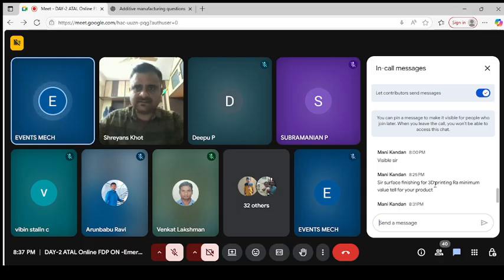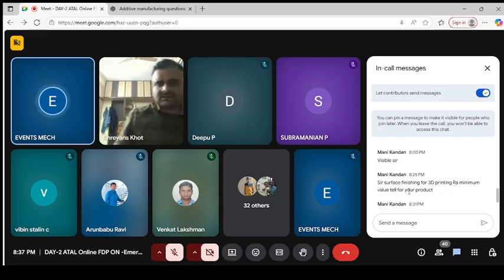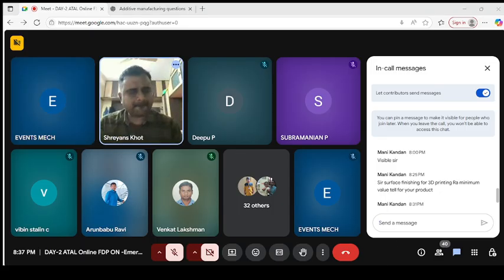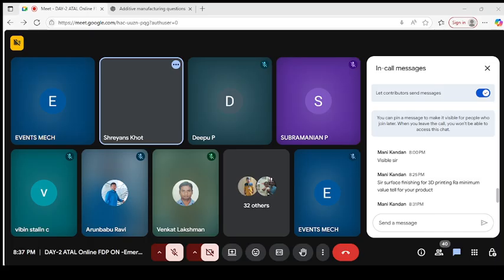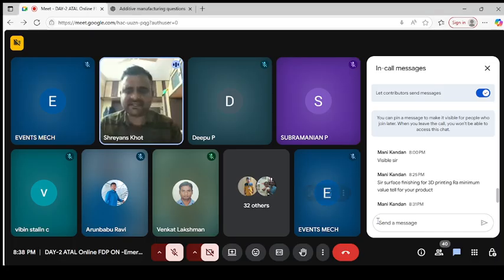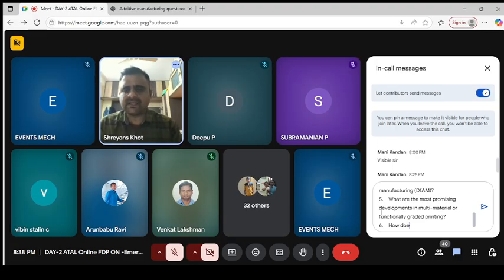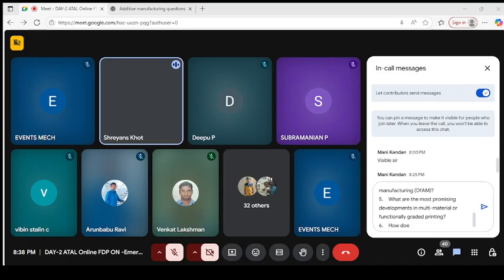Surface finish for 3D printing, or minimum value for your product. So he's asking about the surface finish of the product you have shown in your case study. Good questions. See, I will tell you, if I print aluminum AlSi10Mg, it is a lightweight material. During printing, it will agglomerate the surrounding particles. So as printed, we can achieve 7 to 8 Ra. After polishing, shot blasting and glass bead blasting are available, where we can improve up to 1 to 2 Ra. For SS316, as printed with 30 micron layer thickness, we can achieve 3 to 4 Ra.